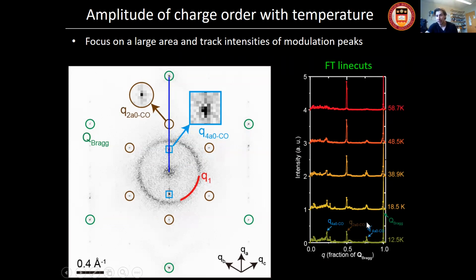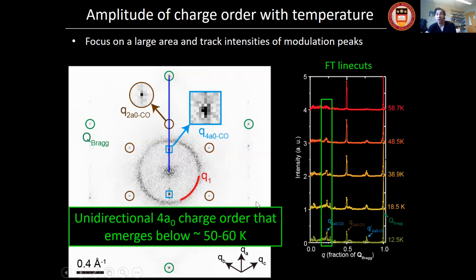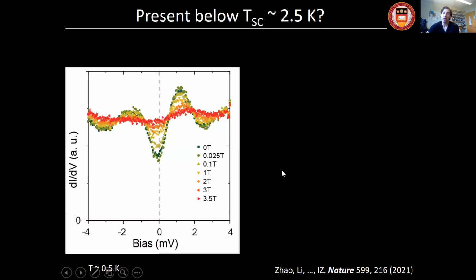Halfway to the atomic Bragg peak is our 2x2 charge density wave state. That again exists at 60 Kelvin, and it is still there as you cool down. And this little peak here is our 4A0 charge ordering peak. If you look at what happens as a function of temperature, at about 48 Kelvin it's still there, at 50-ish Kelvin it's still there, and at about 60 Kelvin it disappears. So it is a new modulation or new charge ordering state that emerges below 50 to 60 Kelvin.